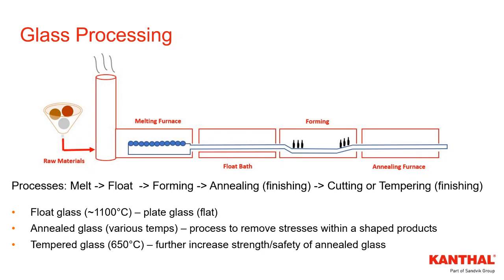A float is a process done at relatively high temperature, 1100 C or 2000 Fahrenheit, and it's the formation of plate or flat glass. Essentially, it's molten glass flowing on a tin bath, and then it's slowly cooled, going through a controlled cooling process to get the right shape and thickness of glass.